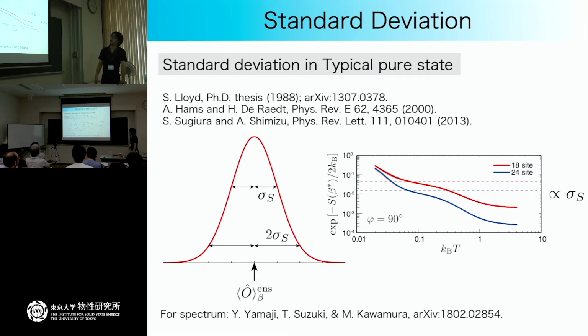If you measure by using this kind of technique, we have really good news, because the error in this finite temperature method scales roughly as the exponential of minus the entropy. If you measure some expectation value of the operators with a typical state at inverse temperature beta, then depending on the initial random state, your observed quantity has a probability distribution like this, and the width is given by the standard deviation. And this standard deviation scales as this exponential of minus the entropy.